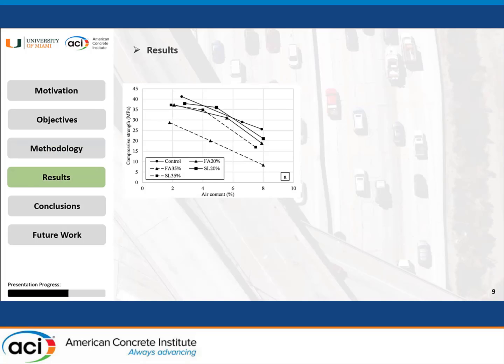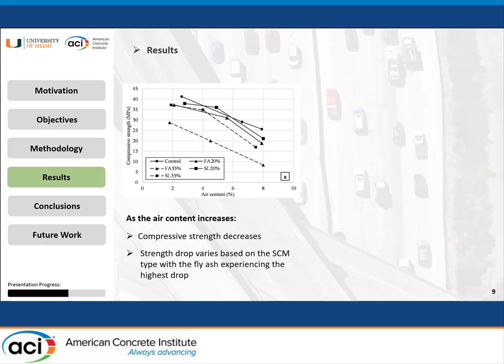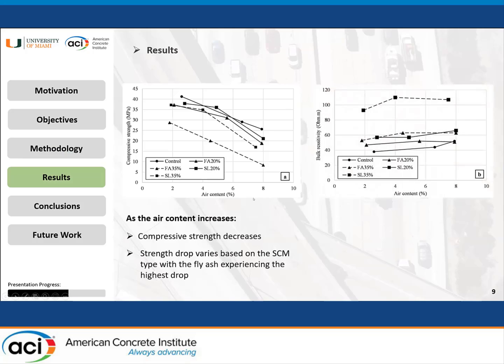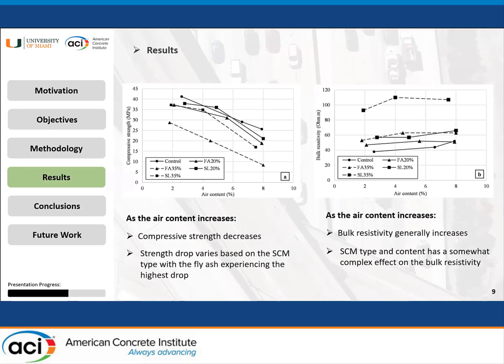Starting with the compressive strength values versus the air content, which was measured before samples were exposed to these cycles. As the air content increases from left to right, you see that compressive strength decreases, and the strength drop varies based on the SCM type. With the fly ash, as you can see over here, you are experiencing the highest drop. On the right side, I'm showing you the bulk resistivity values versus air content. The same from left to right, the air content is increasing, and with this increase, the bulk resistivity is generally increasing, and the SCM type and content has a somewhat complicated effect on the bulk resistivity values.